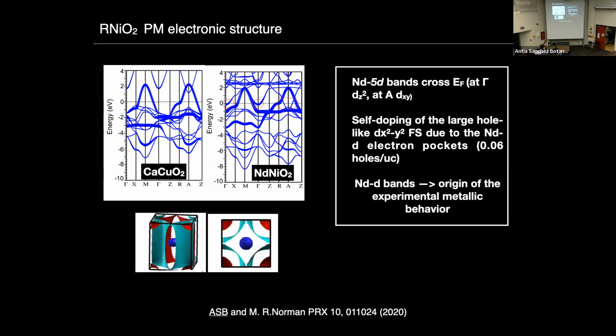So in the nickelate, one starts already at d9 filling from a non-cuprate-like situation, in that you already have self-doping of that large dx²-y² Fermi surface due to these neodymium d bands. And at the time, we thought that these neodymium d bands were indeed the ones at the origin of the experimentally found metallic behavior, which is something upon which there is an agreement now.